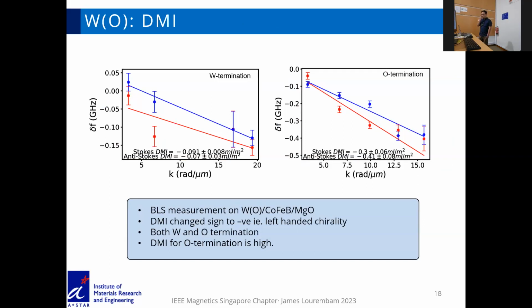In terms of DMI measurement, this work is currently ongoing. I've shown in the previous example that whether we use tungsten or tungsten tantalum or other formats based on tungsten systems, we always got positive DMI. But in this tungsten multilayer system, we got a negative DMI. This was measured by Suraj at NUS. We're still trying to figure out why the sign of the DMI in this system has changed. And the value is also different in the case of oxygen termination, which was found to be higher than tungsten termination.